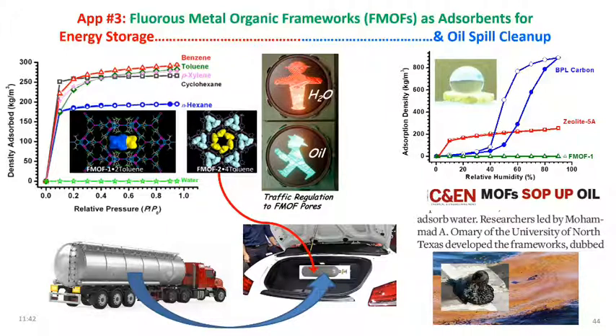Activated carbons like BPL, that's supposed to be hydrophobic, just carbon, right? They resist humidity only up to 40%. More than 40%, it picks up water, even becomes worse than zeolite. Yes, the activated carbon is supposed to be just pure carbon.